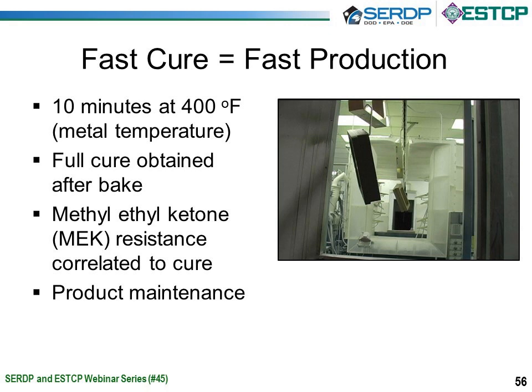So where did we end up? Marc and Jim had both talked about where we started and how we moved to our final product. The fast cure means fast production. A typical coating, if you're looking at, for example, a military coating, is a 250 bake for 30 minutes. Or if you're looking at an ambient cure condition, it can take 4 to 7 days or up to 10 days depending on the technology you're using. Fast cure means fast production.